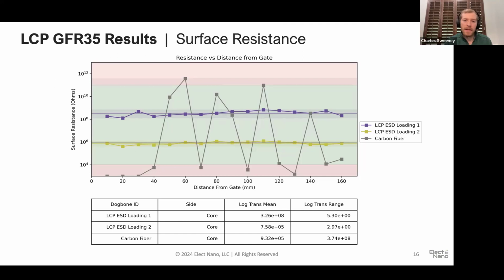We can dial in a specific surface resistance that we want. We don't have to try to average everything out, and we hit it within a single order of magnitude. That's really the game-changing opportunity for nanoscale materials: they average out all the hot spots and cold spots, and you just get consistent uniform properties throughout the entire component.